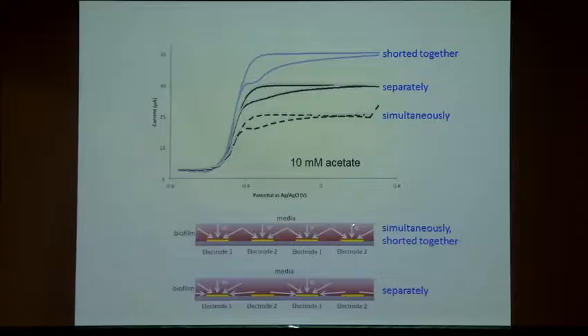I really haven't done anything differently. I'm just measuring the sum together, or I'm measuring them separately and adding them together. But if I actually do this configuration here, where I only sweep electrode 1 and leave electrode 2 at open circuit so I can't gather electrons, then I get a catalytic voltammogram like this. And what's interesting is I'm actually collecting more current at this electrode, so the current density at this biofilm electrode interface is actually higher here than it is here.